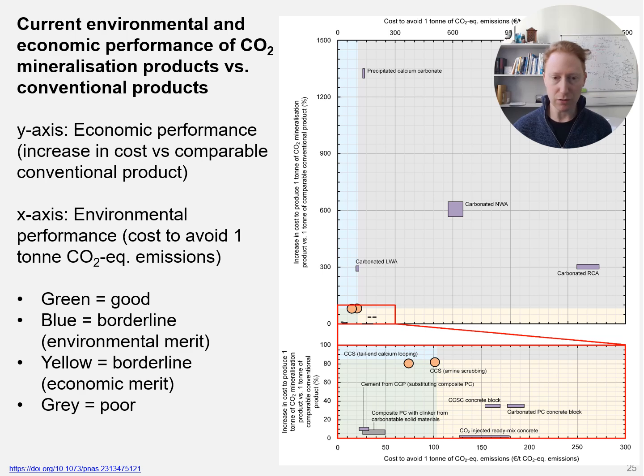The orange circles are carbon capture and storage technologies applied to cement production, and they are here: amine scrubbing and calcium looping. And so that means that the technologies in the bottom left, which are in the green region, are those that are better than carbon capture and storage. The technologies in the top right in the grey region are worse than carbon capture and storage, and the technologies in the blue and yellow regions have borderline economic or environmental performance.